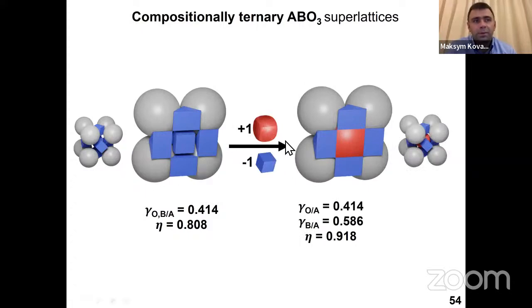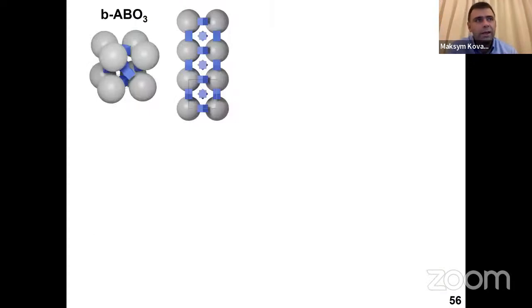And to show you yet another possibility, you can start building fully ternary lattices, where also the center cube can be a different type of cube. If you take a mixture of smaller cubes and larger cubes in a specific particle number ratio and size ratio, you can build a lattice where preferably a bigger cube will go into the center of a unit cell, because crystallographically this site is a little bit larger, and therefore for geometric fitness this cube will go over there. So this is very tedious experimental work because you need to control the sizes very precisely, but once you do that, you can produce such ternary structures as well, and you can fully characterize them.